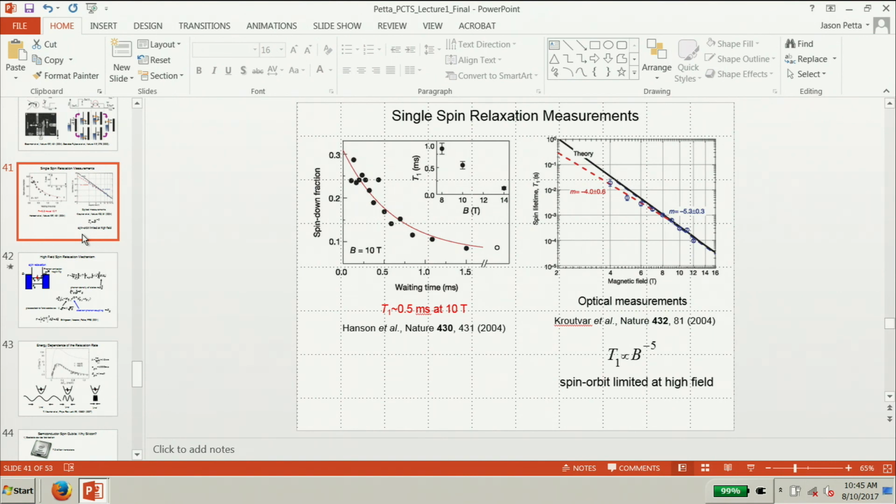Yeah, I think the main challenge for us has been decoherence. A lot of the early work was done in gallium arsenide because you had access to very high quality two-dimensional electron gas and could do these single qubit experiments. But the spin dephasing times were so short that when Tarucha's group and other groups tried to implement a CNOT in gallium arsenide, you would maybe see a 15% change, like visibility in terms of the quantum state. So if you try to do a 4-qubit experiment where your 2-qubit gate barely works, you're basically shut down. And that's where we were at for the past 5 or 6 years.